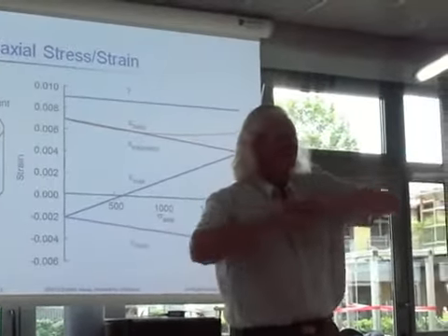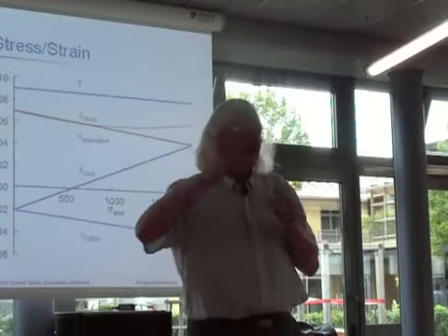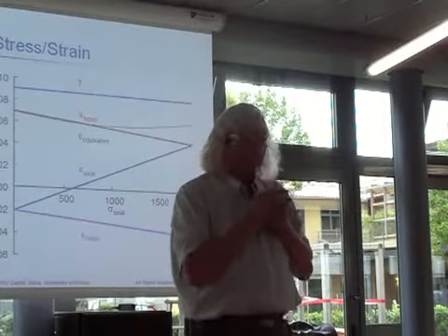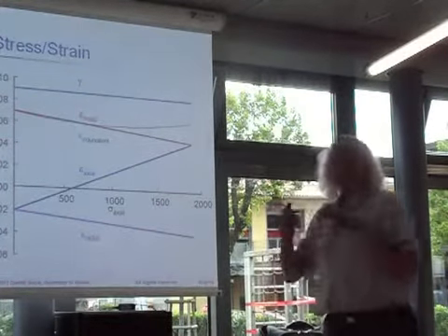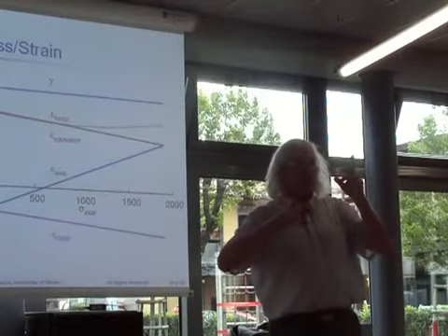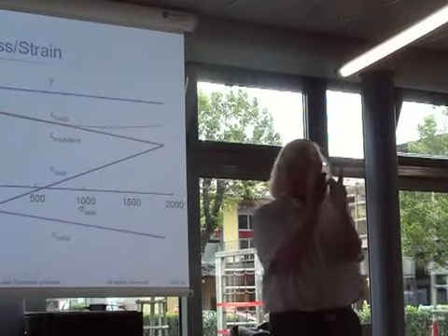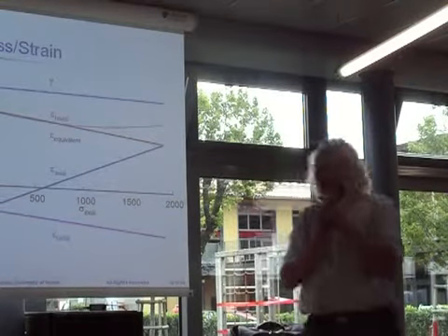See, you will never forget this now, right? A 20% change will move the lifetime two and a half times. So it does make a big difference if you work in stress or strain, if you work only in one dimension, because all the strains are connected. All the strains are connected.